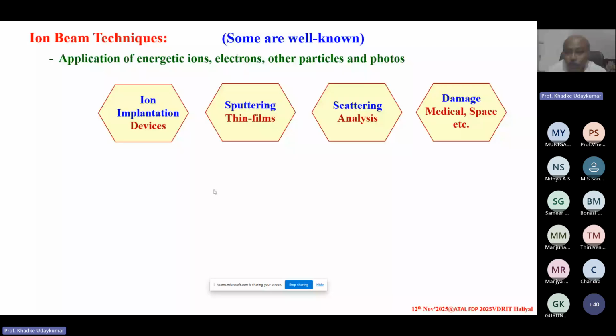But the thing is that you need a specific type of material, usually hard material. When you have hard material, either a semiconducting material or a conducting material is considered to be hard material. And when you put energetic ions on the surface, the atoms on the surface will get sputtered and erosion will take place. And that erosion will be very, very fine, having a dimension of the eroded area of the order of a few nanometers.